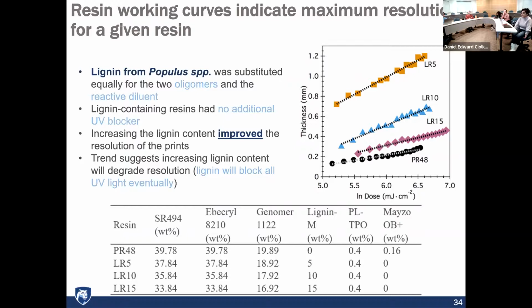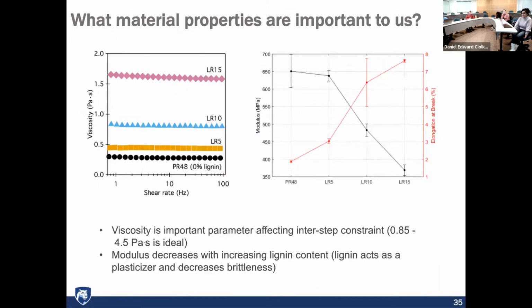We would have thought it'd be the other way around. As you add more lignin, the resin becomes darker, it becomes harder to print with. It seems like it actually becomes easier to print with as we add more lignin, which is great news. It almost never works that way, right? Like you say, oh, well, you use lignin because it's sustainable, but the stuff doesn't work as well. But in this case, we added more lignin and it actually worked better. So that was really great news.